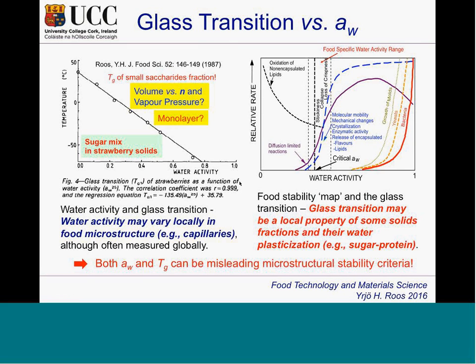I have here something about water activity and the food stability map. Some studies I did a long time ago relating water activity and the glass transition for complex solids such as sucrose in strawberry solids. So it is a linear relationship, but that relationship is practically quite useful because you can always have a slope and predict, if I have a water activity of 0.2, where is the glass transition? We know that this would not be stable. And freeze-dried strawberries, if you have ever seen them, are quite fragile and nice when they are at low water content, they are crispy. And if you look at the temperature here, room temperature, it's almost zero water content.